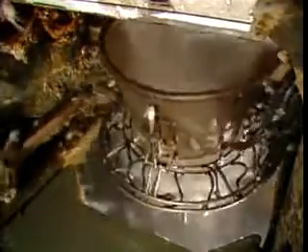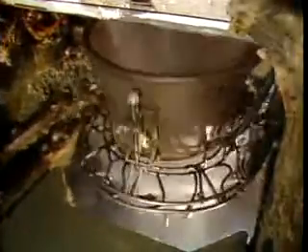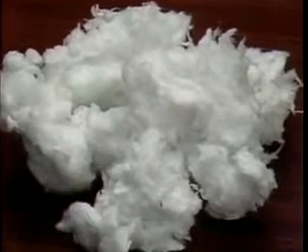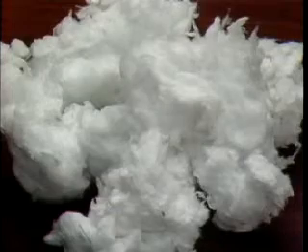where in a single operation it is spun with tremendous force, cooled, drawn into thin glass fibers, and sprayed with a binder which will hold the fibers together in the finished product. As the fibers collect on a conveyor, they build up into a continuous mat of insulation, which later down the production line will be cut into lengths and packaged into bats and rolls. Another separate series of fiberizing machines produce InsulSafe, CertainTeed's premier blowing insulation.